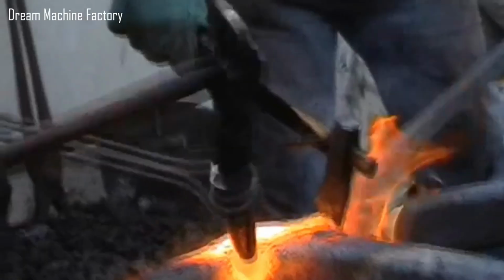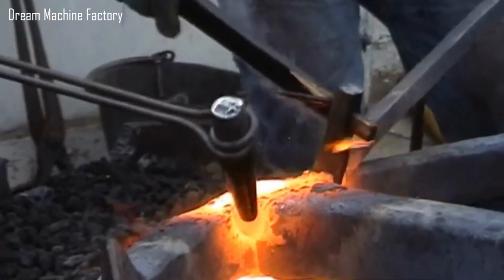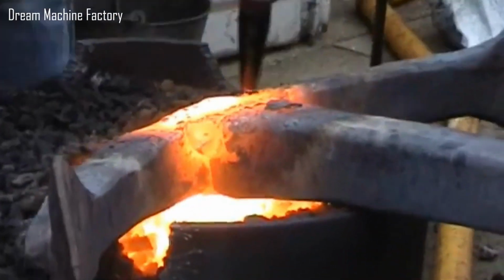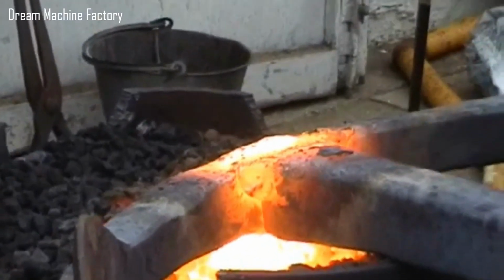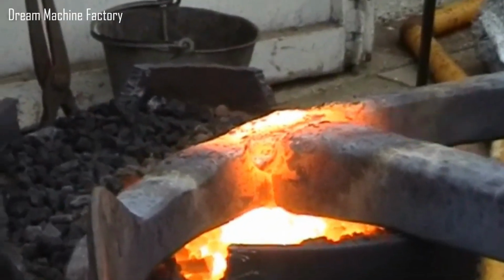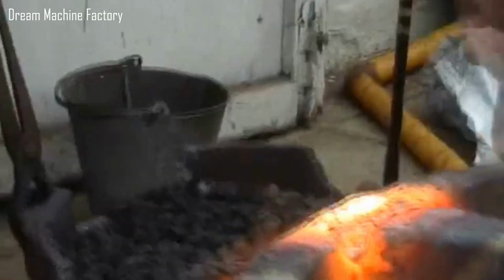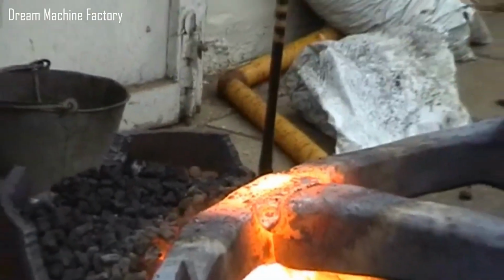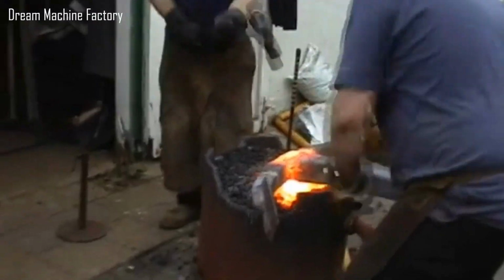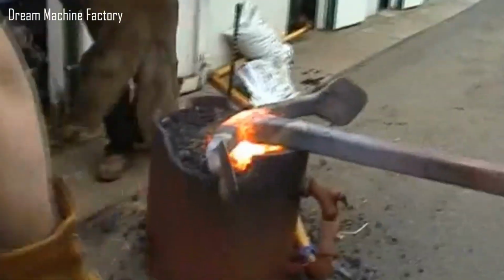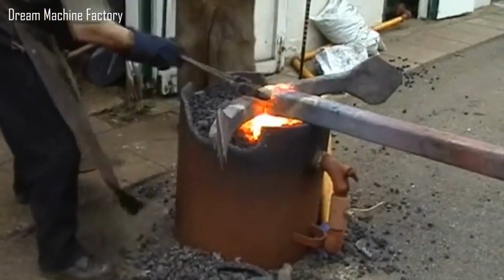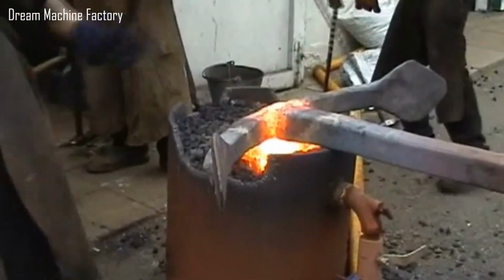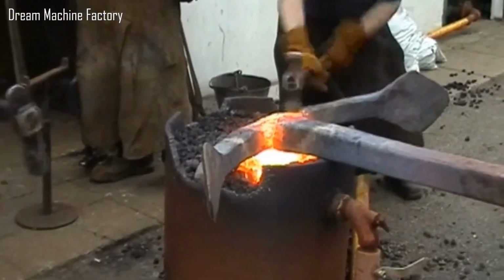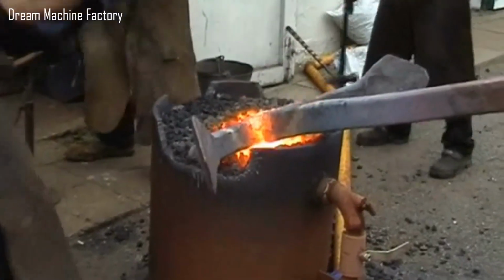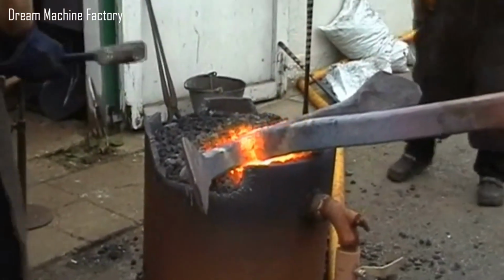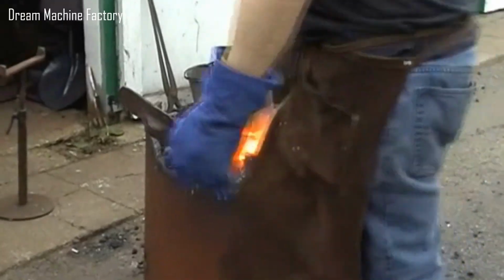The welding itself requires quick, decisive hammer blows. The smith brings the heated components from the forge and positions them precisely, then strikes firmly to drive out any remaining flux and scale while ensuring the metals fuse. For an anchor, the main welds are usually between the shank and arms, where strength is most critical. Multiple heats may be necessary, especially for thicker stock, as the weld must be consolidated gradually to avoid cold shuts or cracks. After the welds are secure, the anchor is reheated and shaped to its final form.